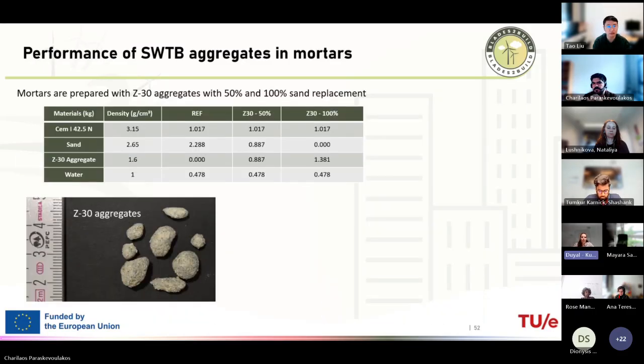To assess more, we also put these aggregates inside of mortar and tested the mortar properties. We selected the best performing aggregates, which is Z30, and here is the recipe for the mortars that we prepared. We replaced 50% of the sand and 100% of the sand with these artificial aggregates. And there was an interesting result on workability.